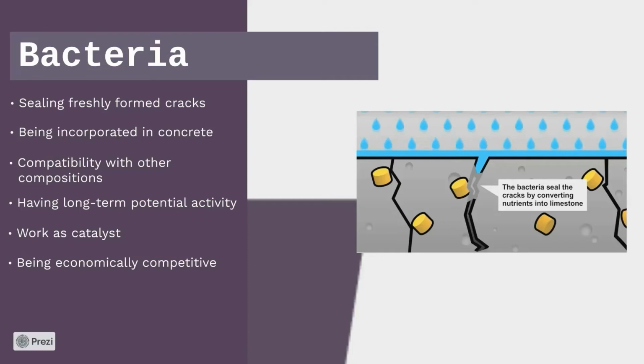These agents will commence activating by the ingress of water that happens due to the cracking. Then subsequent calcium carbonate formation results in the closure of microcracks up to 0.46 millimeters after 100 days, which is approximately 2.5 times greater than the closure in OPC concrete. Also, consuming oxygen by bacteria dwindles the probability of steel reinforcement corrosion.